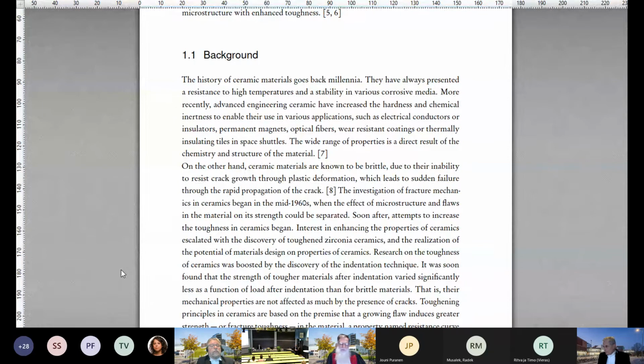So let me dig a little bit deeper. This is a question that I ask myself every time with regards to ceramic coatings. Are cracks good or bad? Is porosity good or bad? Is there a mix of these voids which may actually increase strain tolerance? What are your thoughts about that? And then I'll hand it back to Jari. Okay, that was a good question or comment. As I mentioned in my lecture, there's industry pull for developments often, and in my case, we wanted to have also dense wear-resistant coatings with higher strain tolerance. So in our case, cracks and voids generally would be deleterious, so unwanted.